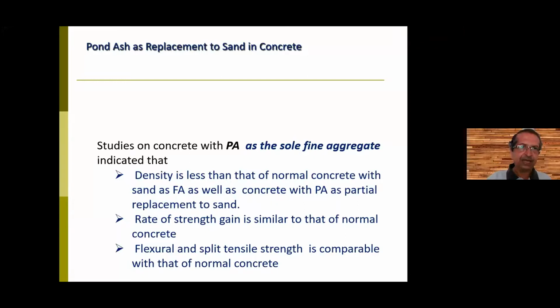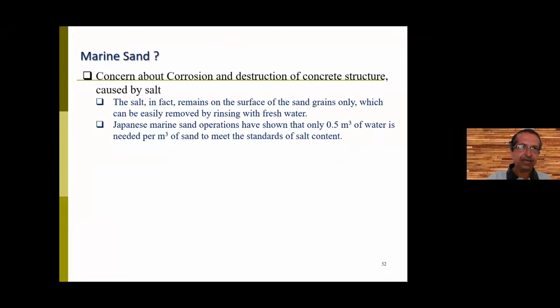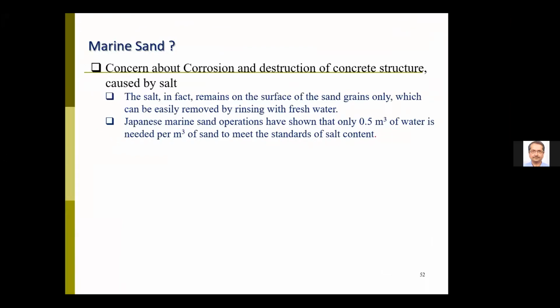But by using particle packing theories and modifying the coarse aggregate to fine aggregate ratio, we could achieve concrete of M25, 30, 35. People have tried using marine sand. Of course, there are concerns about corrosion and destruction of concrete structures, but the salt, in fact, remains on the surface of the sand grain only, which can be easily removed by rinsing with fresh water. In Japan, they found that about 0.5 cubic meter of water is required per cubic meter of sand to meet the standards of salt content in sand.